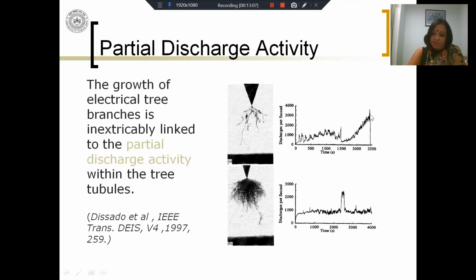At the end of this PD activity, you see that the tree has grown considerably. It has become a completely bushy tree which has almost occupied the entire space in front of the needle, and then there are some filamentary channels which are continuing to progress and reach the other electrode, and the PD activity is continuing. The nature of the PD activity has changed, but we still see PD activity taking place. So whenever you have an electric tree, you have PD activity inside the tree channels.